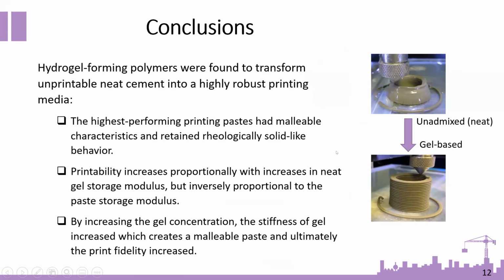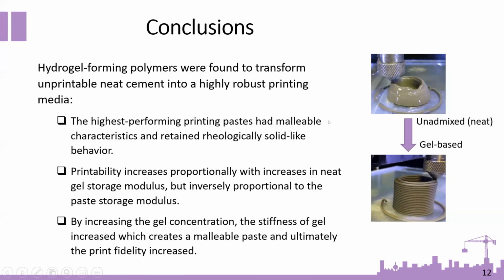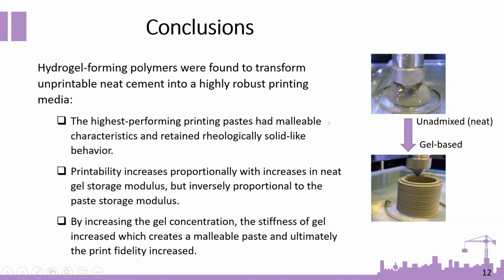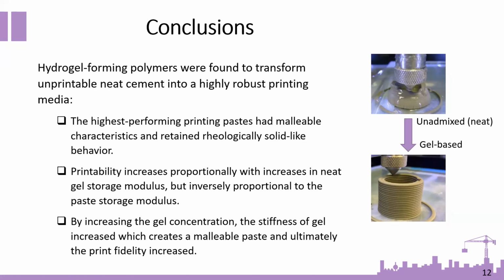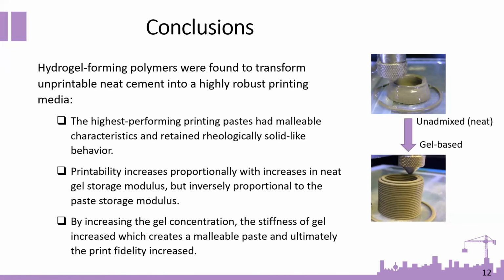So all in all, hydrogel forming polymers were found to transform unprintable neat cement paste into a highly robust printing media. The highest performing printing paste had malleable characteristics and retained rheologically solid-like behavior. Printability increased proportionally with increase in neat gel storage modulus, but inversely proportional to the paste storage modulus. By increasing the gel concentration, the stiffness of the gel increased, which creates a malleable paste, and ultimately the print fidelity increased. And thank you for your presentation.